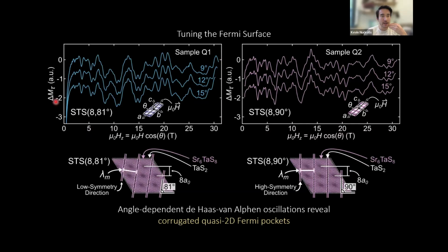And so we plot here the background subtracted torque magnetization, which just gives me the oscillatory portion of the torque magnetometry signal as a function of magnetic field up to 32 Tesla, as given to us at MagLab. You can look at these quantum oscillations, and you can see that they look very similar, but they're clearly different, even just from the oscillation point of view. You can see that these signals are different.